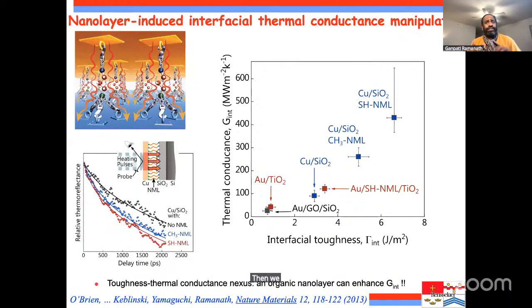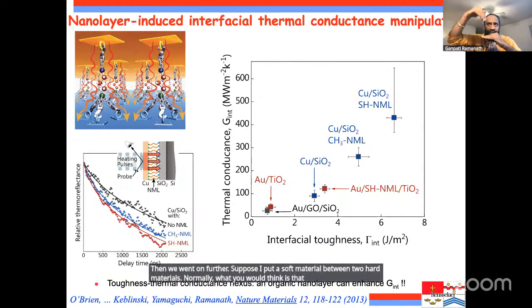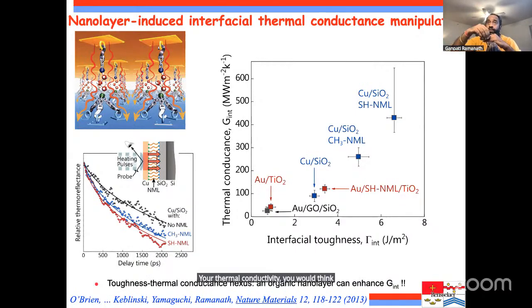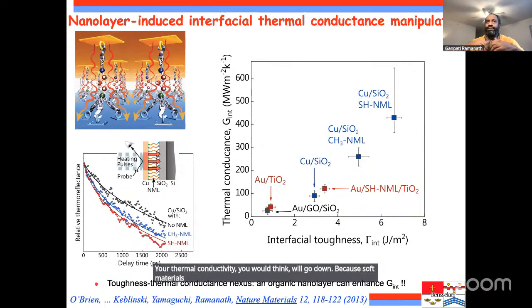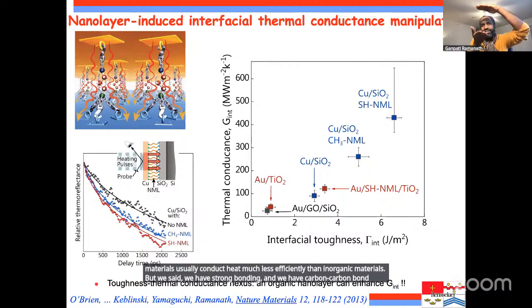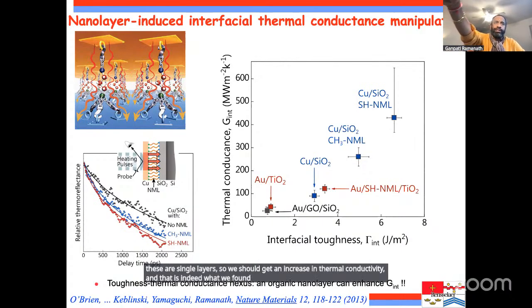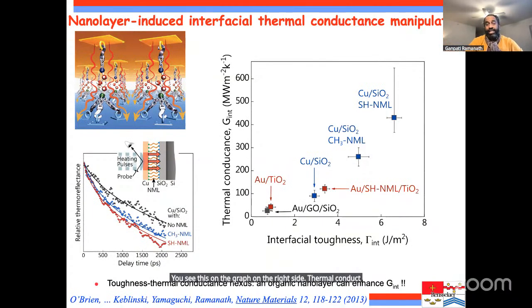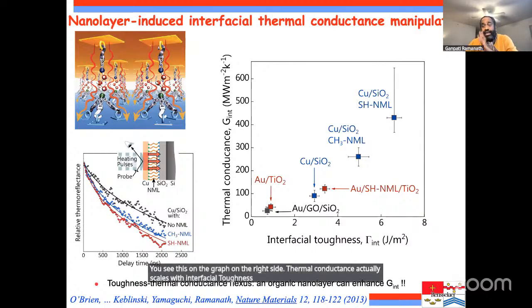Then we went on further. Suppose I put a soft material between two hard materials. Normally, what you would think is that the adhesion would actually go down, but in this case, the adhesion is going up, and also your thermal conductivity you would think will go down, because soft materials usually conduct heat much less efficiently than inorganic materials. But we said we have strong bonding and we have carbon-carbon bonding, and these are single layers, so we should get an increase in thermal conductivity, and that is indeed what we found. You see this on the graph on the right side. Thermal conductance actually scales with interfacial toughness. And this again was a fundamental breakthrough that was not known, so it got us another Nature paper.